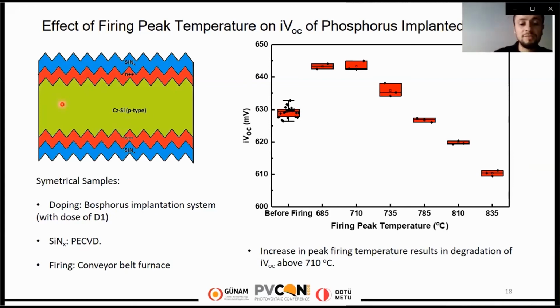The samples were implanted with dose D1, the lower dose, by the Bosphorus ion implantation system in Yunan. Then PECVD nitride was deposited on both sides. The samples were fired in a conveyor belt furnace to release hydrogen from the silicon nitride.